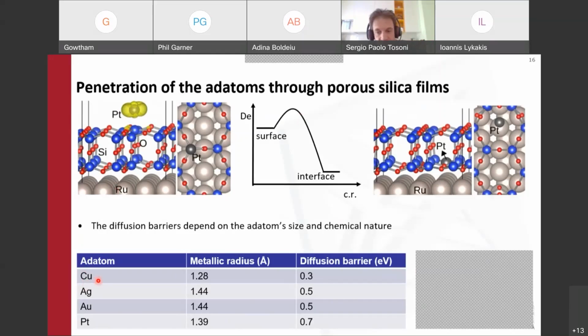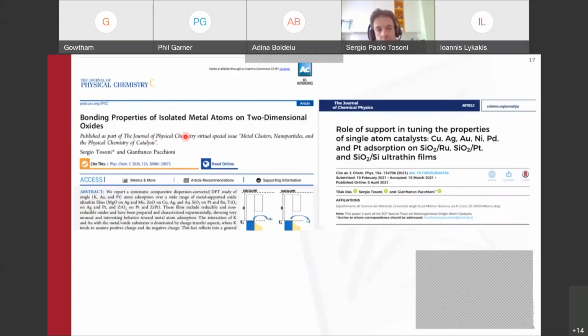And we did this for a series of atoms spanning from copper, silver, gold to platinum. As you can see, we find a remarkable dependency of the diffusion barrier on the metallic radius of the species. The diffusion barrier is small, 0.3 electron volts, for a small atom such as copper, while if we increase the metallic radius, we get almost an increase by a factor of 2 of the diffusion barrier. So these are the two papers summarizing our main findings. They appeared over the last 2 years in the Journal of Physical Chemistry C and the Journal of Chemical Physics.